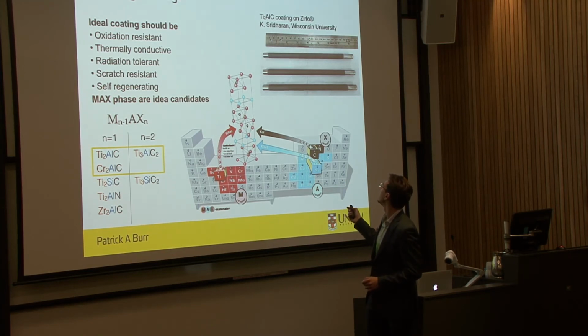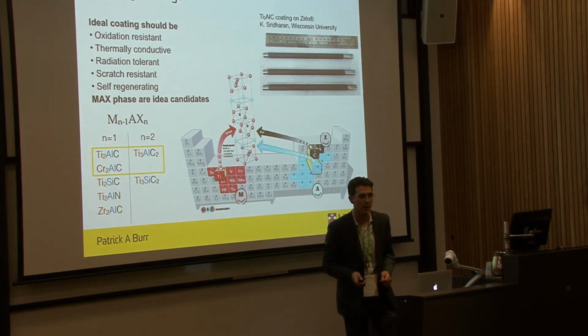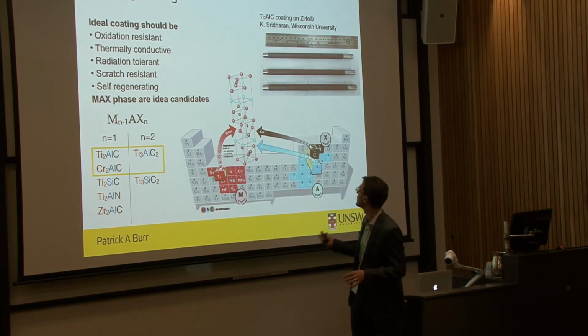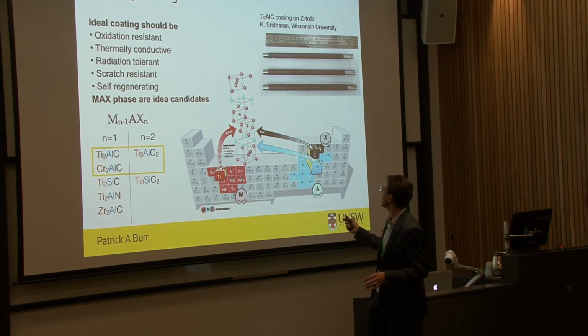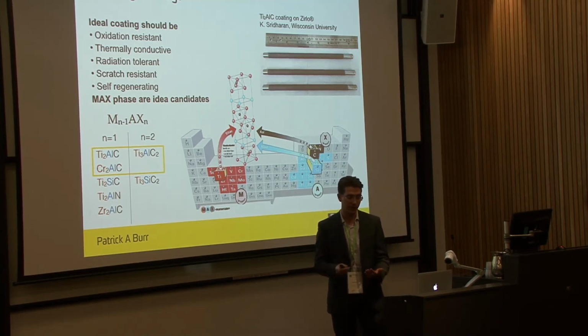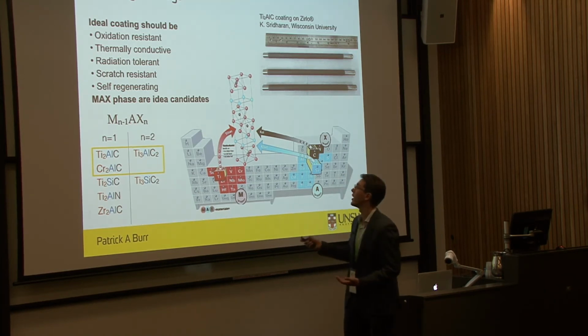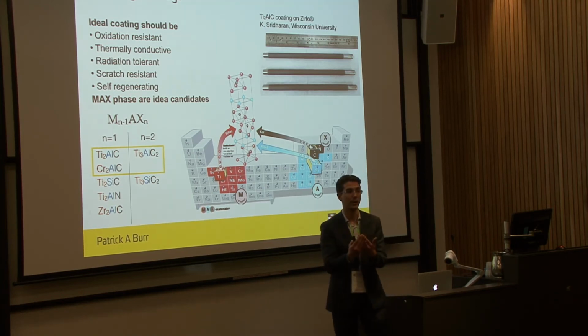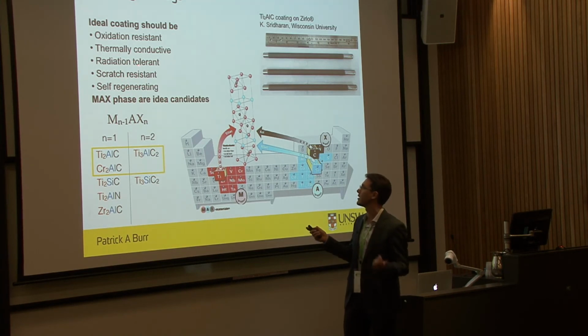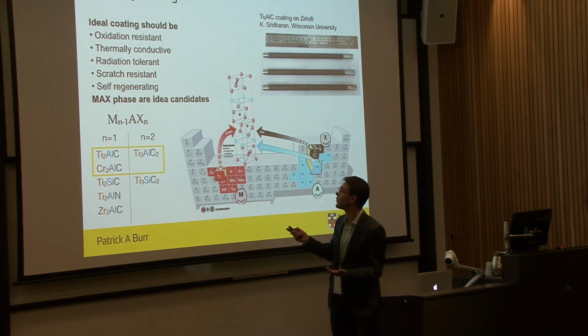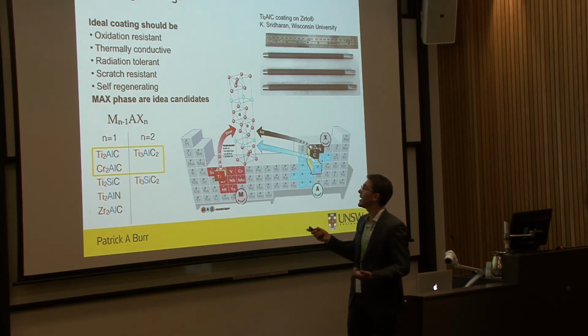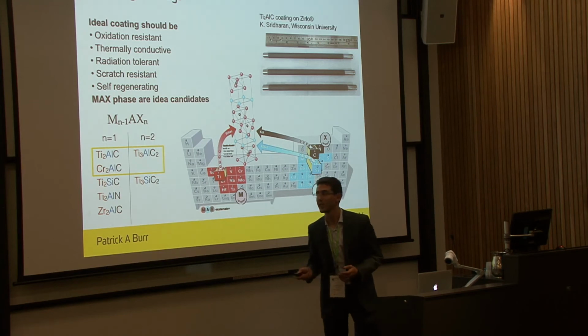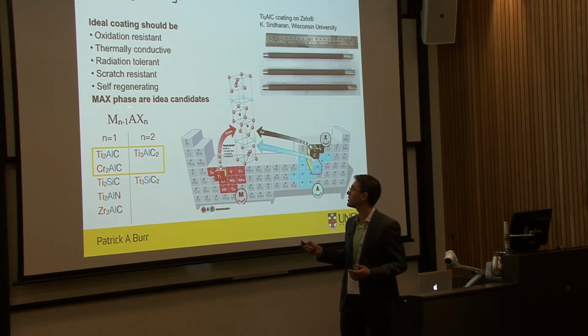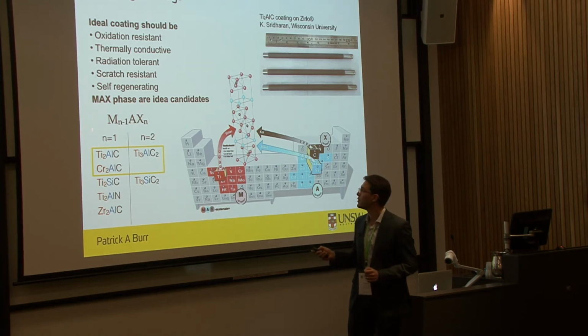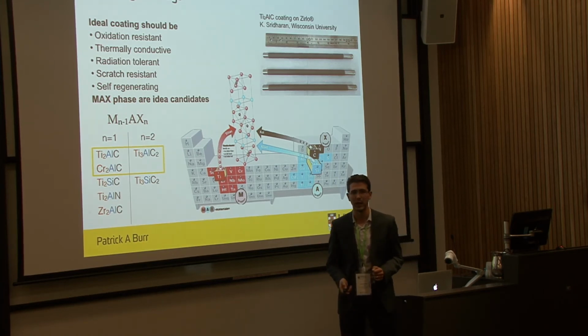This is a picture from Wisconsin University where they, in fact, have coated it with titanium aluminum carbide, which is a MAX phase. I'll explain in a second what these are. And the aim of this coating is to have something that is oxidation resistant, but at the same time it has many other criteria that it has to satisfy. It has to be thermally conductive, otherwise you create a thermal barrier to the extraction of heat. It has to be relatively radiation tolerant, scratch resistant, possibly self-regenerating in case you scratch it. And on top of that, it has to be neutron transparent. So we're really asking a lot of this coating. And there's a particular class of materials that seems to nearly satisfy most of them, which is MAX phases. MAX phases are essentially ceramics.